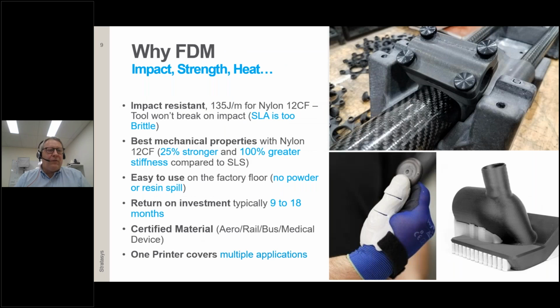It's very straightforward. It's about a few very important points. It's impact strength and heat resistance. Impact resistance, for example, for the nylon 12 carbon fiber, which we are using on the 450 and 900s, is fantastic if you compare it, for example, to SLA, which is far too brittle. With the nylon 12 carbon fiber we have the best mechanical properties, which is more than 25% stronger and 100% greater stiffness compared, for example, to SLS.